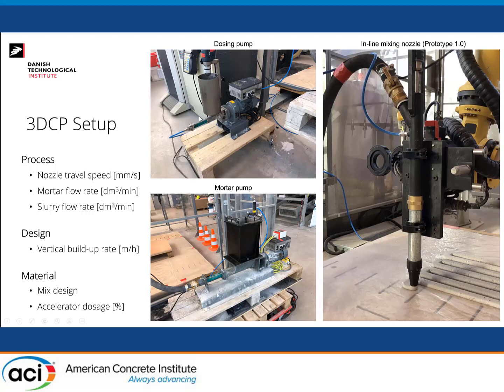Okay, one final question. Can we use this inline mixing nozzle to print fiber reinforced cementitious composites? Not as is. Well, you could, but I could not share, unfortunately, the details of the mixing blades. But if you modify the mixing blades, and depending on which fiber length and which volume of fibers you're talking about, yes. But I tend to go away from fibers at the moment because it becomes priority number 2. I would just be adding more complications to the system. So with a few adjustments, yes.